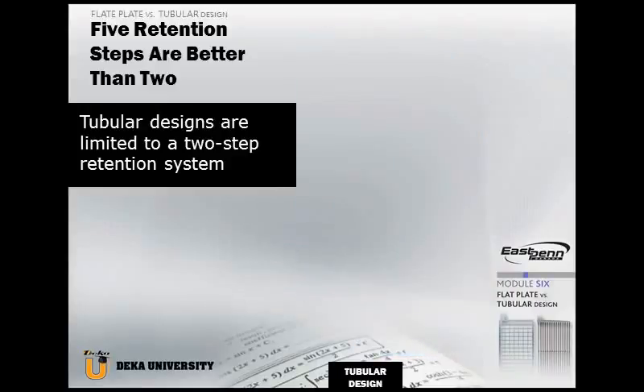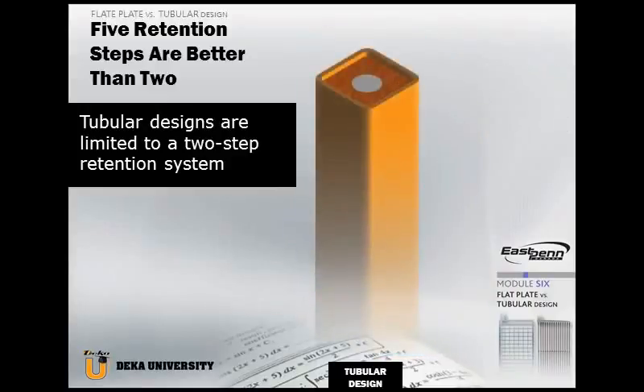Another problem that can occur with limited retention is split tubes. Through excessive discharging and recharging, the active material can swell and increase pressure on the tube. A split tube results in catastrophic shedding, leading to significant capacity loss.